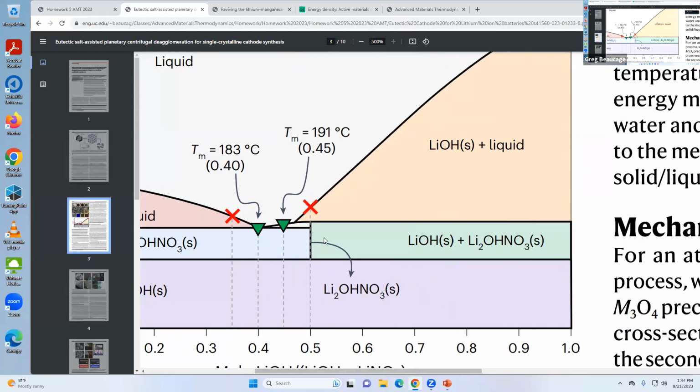Can't blow up anymore, I don't think. So basically, between the top and the bottom here, because that's 183 and this is 191, you're at 187. So you'd form, and then if you did an equilibrium line, the liquid part, well, it's mostly liquid. So it would be liquid with little precipitates of this intermetallic forming. Yeah, it's mostly liquid, sorry. So yeah, it would be just precipitates forming in the liquid phase. So you get a powder coming out of that composition.